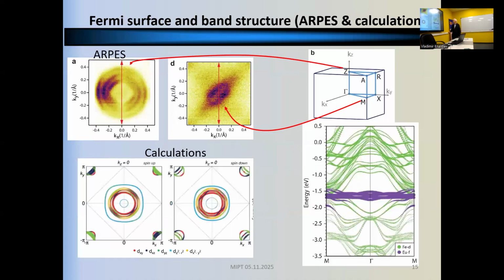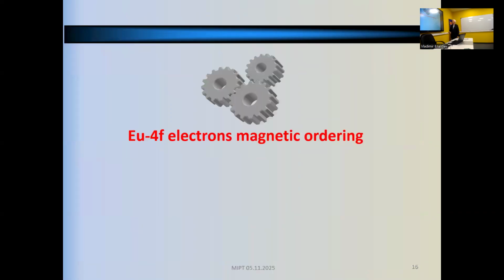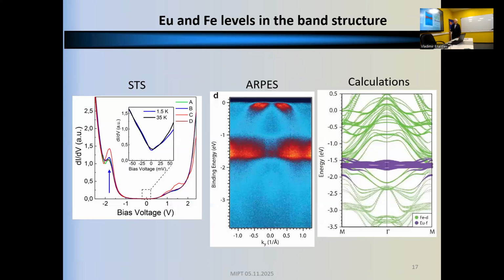What about magnetic layers? The magnetic moments come from europium 4f electrons, and their band is located much deeper, at about minus 1.5, 1.6 eV. As I said, this was measured experimentally by ARPES. You can see here the very powerful band of 4f electrons, and in calculations, and this can also be noticed from scanning tunnel spectroscopy, where some dip in the density of states is related to the